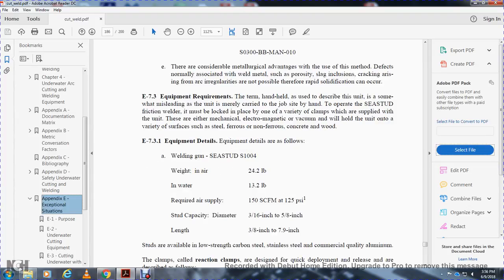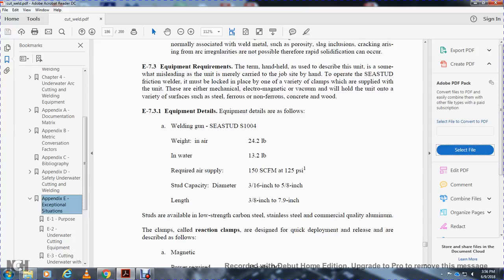E731, equipment details. The equipment details are as follows: welding gun SEASTUD S1004, weight in air 24.2 pounds, weight in water 13.2 pounds, required air supply 150 SCFM at 125 psi, stud capacity diameter 3/16 of an inch to 5/8 of an inch, length 3/8 of an inch to 7.9 inches. Studs are available in low-strength carbon steel, stainless steel, and commercial quality aluminum.